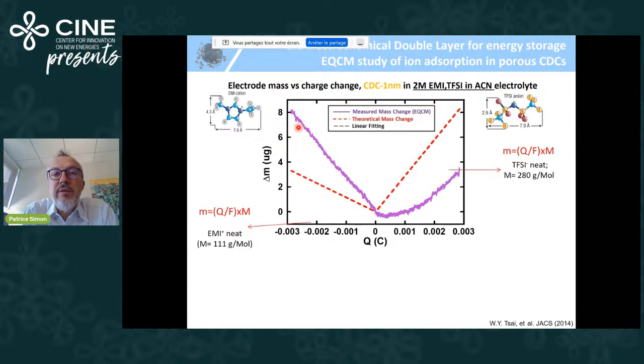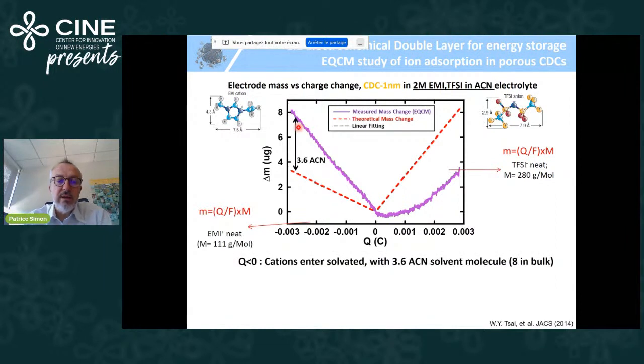So it means that we have heavier ions which are adsorbed, cations adsorbed into our porous carbon. How can you explain that? You just explain that because our cations are entering the carbon pores with solvation shell, with solvent molecules. And you can calculate from experimental to theoretical weight that EMI cations enter with 3.6 acetonitrile molecules into our porous carbon, which I forgot to mention is 1 nanometer pore size.